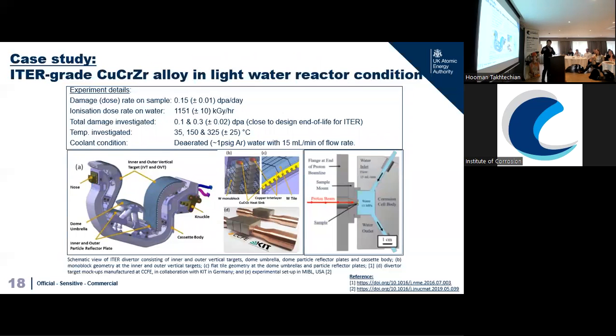So this is just a case study that we did at the UKAEA. We use one of the components, a small component that will be used to build the divertor component itself. This is a tungsten monoblock, as we call it. Basically, it's tungsten material to cope with the high heat flux, and we have a copper pipe, a good heat sink material for us to get the heat out effectively. The problem is that we use copper chrome zirconium alloy because it has better strength than pure copper.